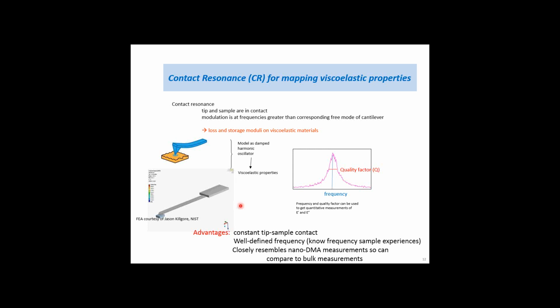So there are several key advantages of contact resonance for nanomechanical measurements. The first is that we have a constant tip-sample contact. It's not like tapping mode or force curve, where the cantilever is out of contact, then hits the sample and then comes out of contact. The cantilever comes into contact with the sample and has a small amplitude oscillation while in permanent contact with the sample. Second advantage, well-defined frequency. We know the frequency the sample experiences because, again, it's in permanent contact with small amplitude oscillation. If we want to compare it to other moduli measurements at a frequency, that frequency factor is clear. And the final thing is that contact resonance closely resembles nano-DMA, so you can compare it to bulk measurements.